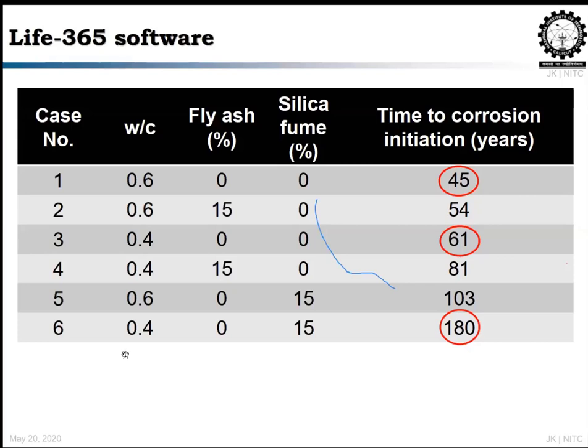If I take case 2, which is with 0.6 water cement ratio but with 15% fly ash, it gives almost 10 years additional. It means 54 years to initiate corrosion. Again, if I go for 0.4 and 15% fly ash, it is 81 years, compared to 45 years.